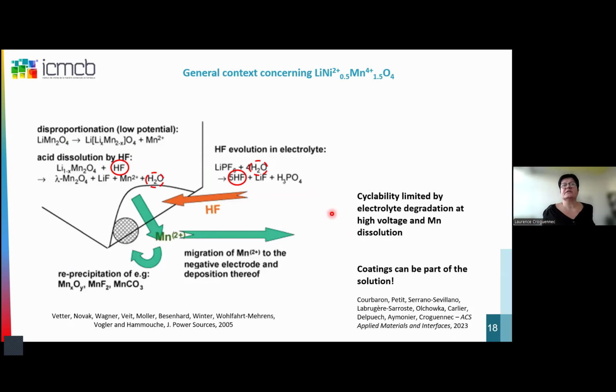I mentioned also the importance of this material. This material is a high voltage material, so it means that we are doing the redox reaction at 4.8 volts. So in a voltage domain where the electrolyte is rather unstable, mostly the electrolyte. Today I will not mention, but in fact, in the literature and in our labs, we have a lot of research also in order to improve and to modify this electrolyte with additives in order to stabilize the interfaces of this material with the electrolyte and the stability of the materials.